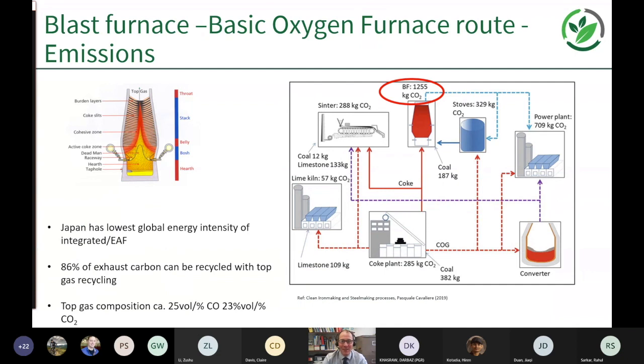So then, looking at producing steel, the iron containing typically about 4% carbon goes into the basic oxygen furnace, where that carbon is combusted off. Overall, for that route for making steel, most of the emissions are associated with iron making in the blast furnace. So I've circled that figure there in the blast furnace of 1200 kilograms of CO2 per ton of hot metal. Now, Japan has the lowest global energy intensity of this route. But potentially, and this leads on to the evolution of the blast furnace, a lot of this exhaust carbon in the form of carbon monoxide, carbon dioxide, can be recycled through the process to be more completely utilized.